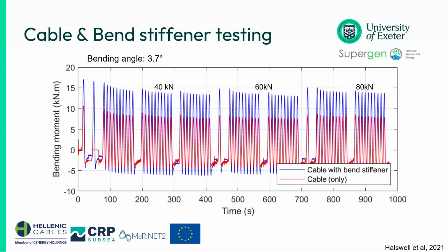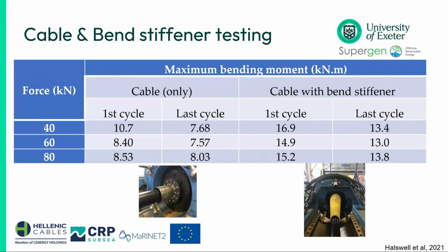And then we've carried on to do a repeated test, and I've got some slides for that as well in a moment. But the main question there is, how do those systems degrade over time? So that's really asking the fatigue question. And for some of those load sequences that we've run, if it's only the cable, between the first and the last cycle there was quite a lot of degradation, certainly for the low tensile ones, and we didn't need as much bending moment in the end. So the bending moment we had to afford was dropping off.